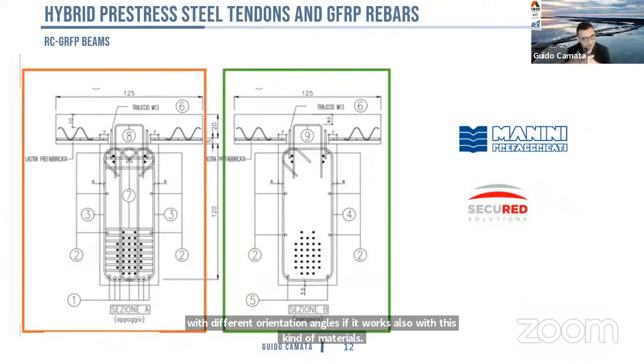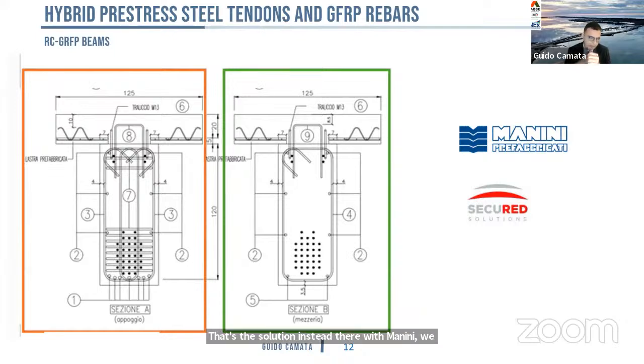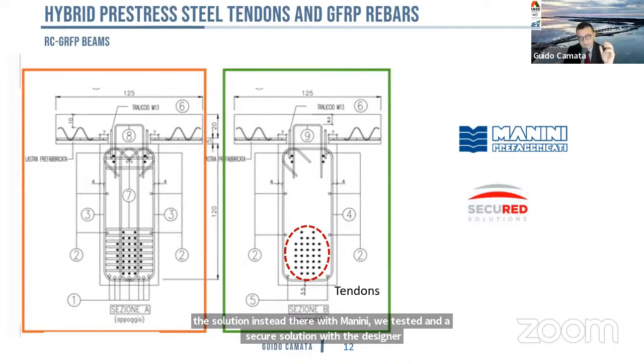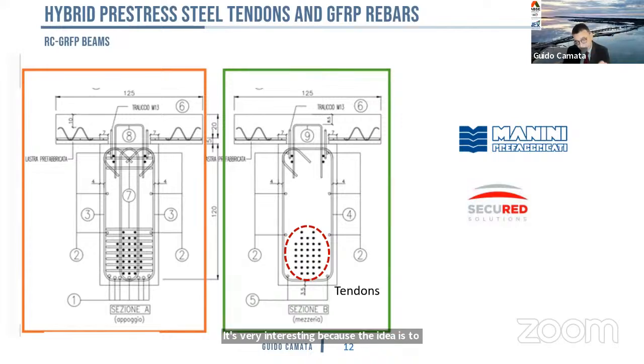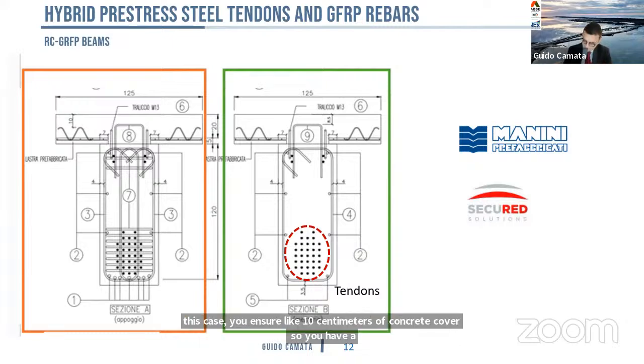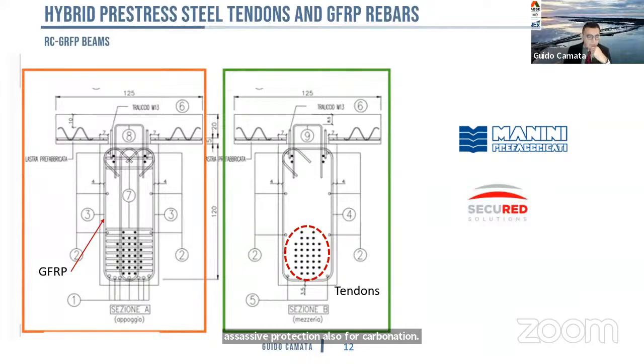That's the solution. Instead, with Manini, we tested a secure solution with the designer that is very interesting, because the idea is to use the tendons for pre-stress at the center of the section. So in this case, you ensure 10 centimeters of concrete cover. So you have an extensive protection also against carbonation. And the external reinforcement is all made of GFRP.